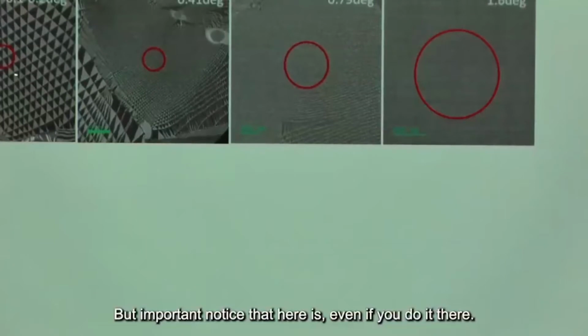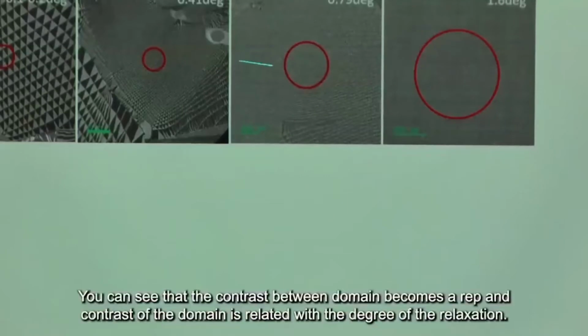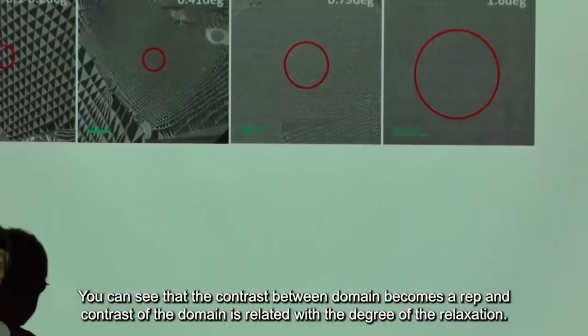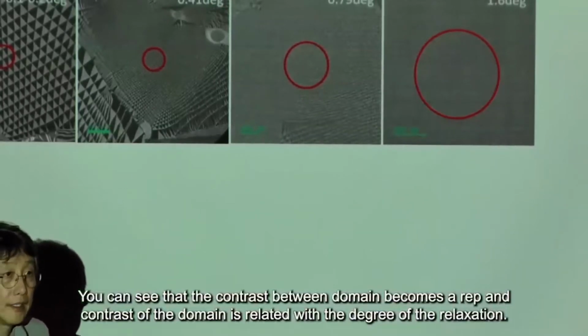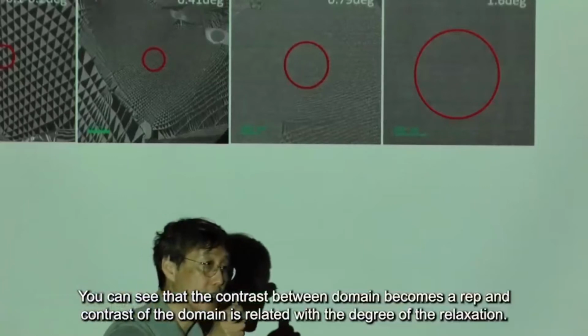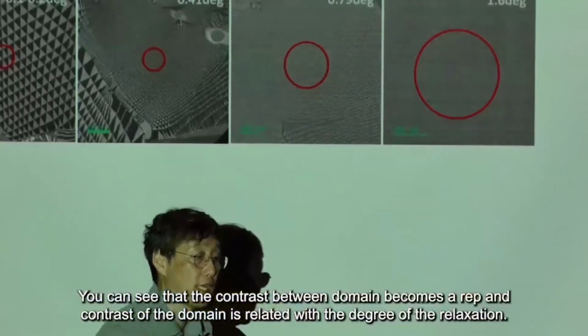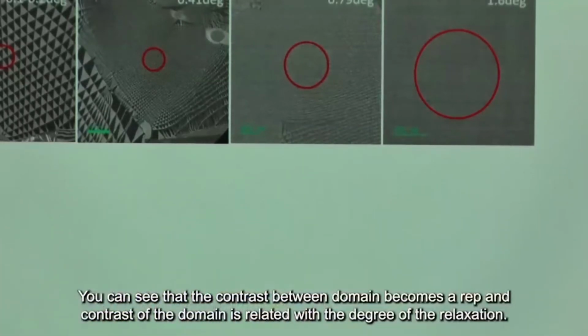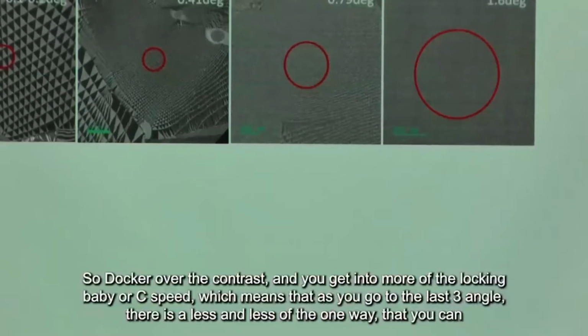But important to notice here is that even if you zoom in, you can see that the contrast between domains becomes weaker and weaker. And the contrast of the domain is related to the degree of the relaxation. The darker and the wider, or the more contrast you get, the more locking into AB versus BA, which means that as you go to a larger twist angle, there is less and less reconstruction happening.